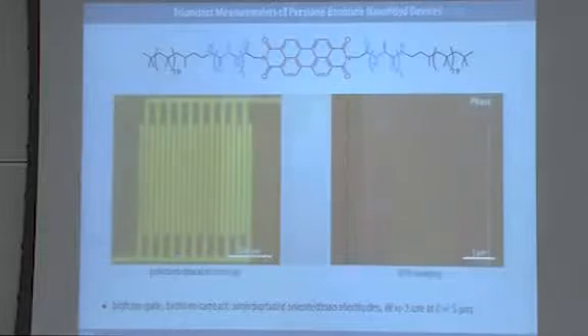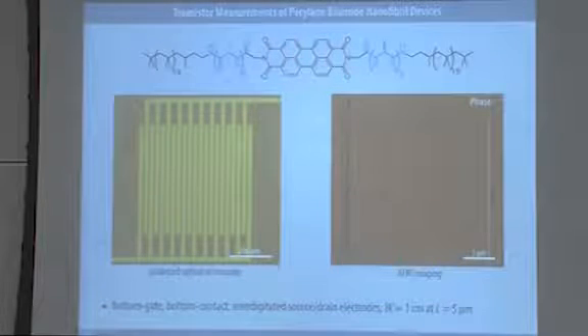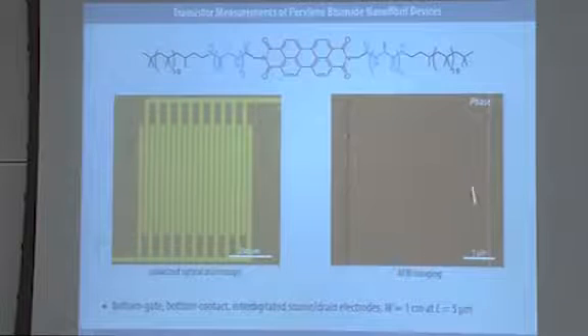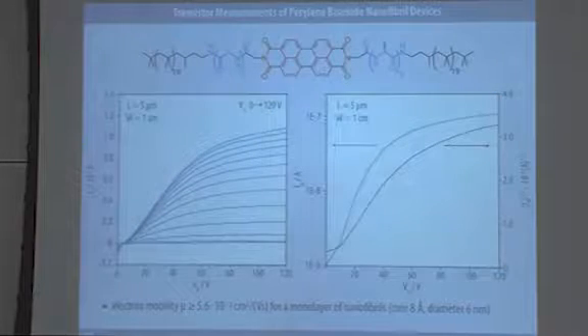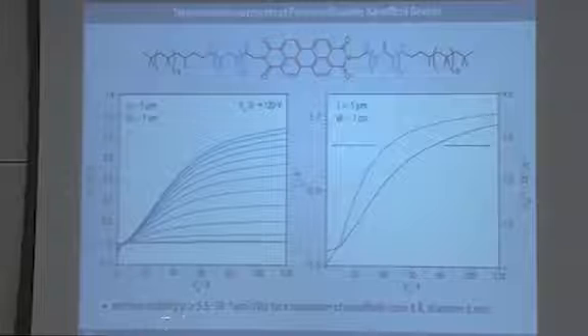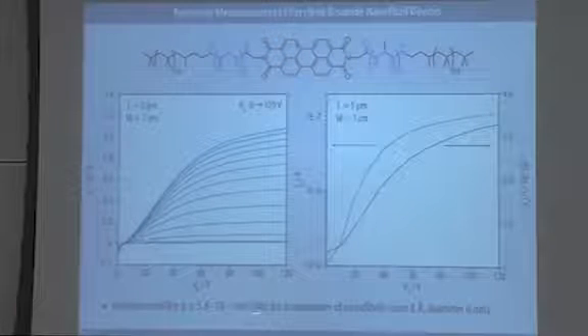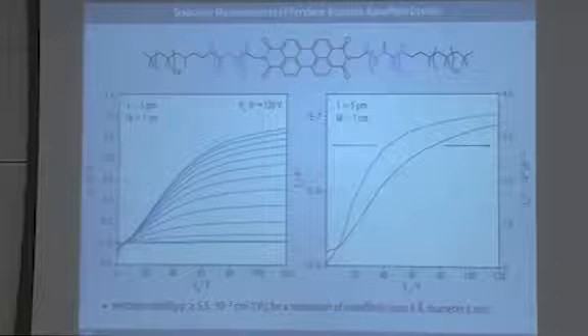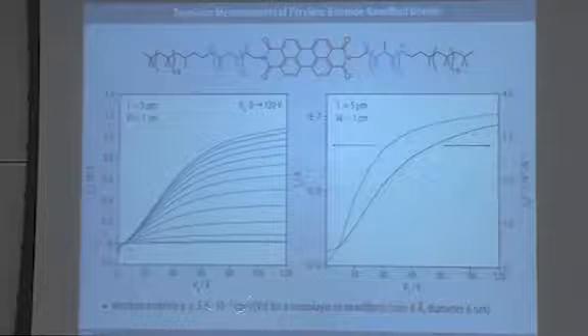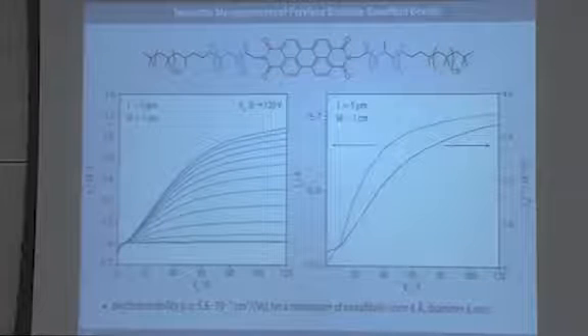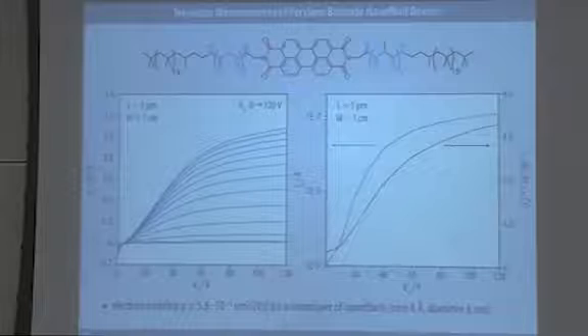And then finally, with the perylene system, we were also successful with building transistors. In this case, we used commercially available bottom gate, bottom contact transistors with interdigitated source drain electrodes, and we just spin coated a dense nanowire film on top, and we obtained decent transistor characteristics, as you can see here, the output curves, the transfer curves, and a first lower estimate of the electron mobility inside these perylene nanofibrils would be on the order of 10 to the negative 3 centimeters squared per volt second, which I find is a decent value. But again, these are very fresh results from the beginning of this week.